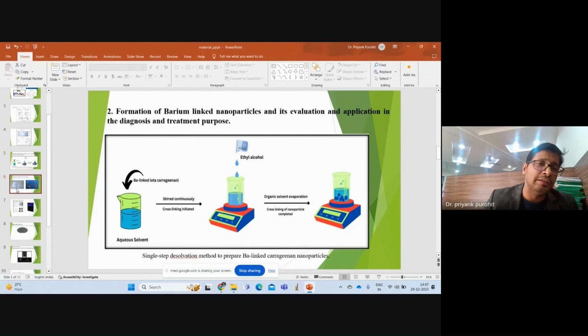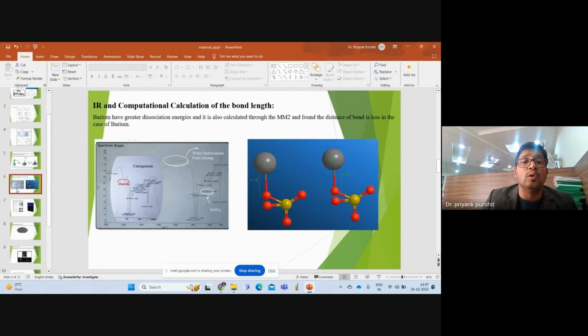We found that whenever we add barium, the water deformation peak was not present. It means water is not there, it means hydrophobicity is there, and everything was similar. If you see the fingerprint region, it was similar, and the bond length was the same. But the problem was how it was not dissociating. So we did studies regarding the barium and published them, that the specific character of barium and its interaction with sulfate is not going to dissociate.